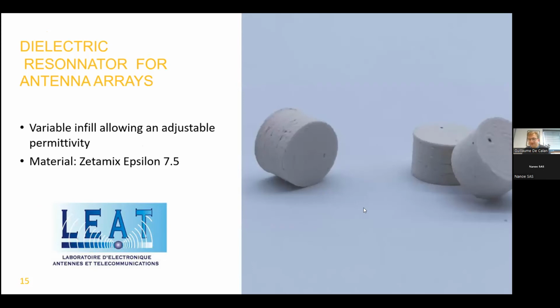Another example here, so I'm afraid we can't really see what's happening in that part. It really looks very simple. These are dielectric resonators for antenna arrays. A dielectric resonator can be used to confine the electromagnetic waves so that you can have arrays of antennas which are relatively close to each other, and that allows miniaturizing the antenna arrays. But to get the maximum efficiency, the LEAT wanted a dielectric resonator with several different levels of density in the same part. So these are very small parts, but inside the part, you actually have three different infills, and these three different infills give you three different permittivities in that resonator.